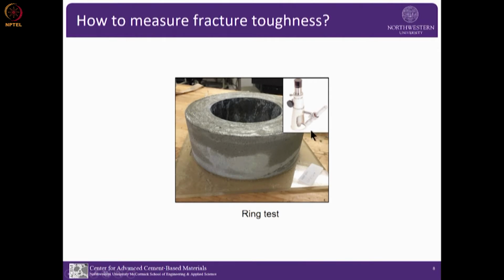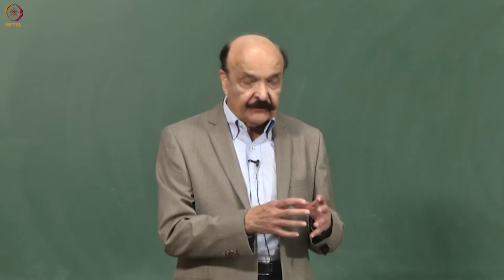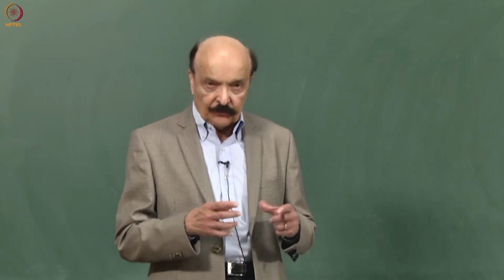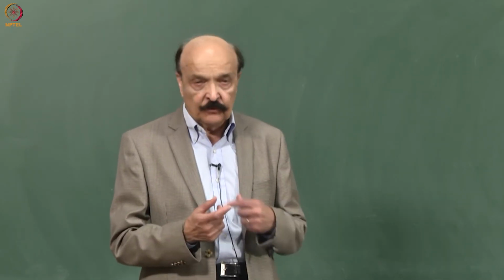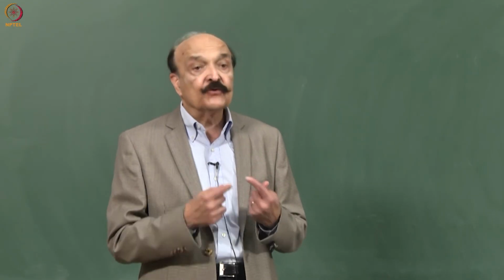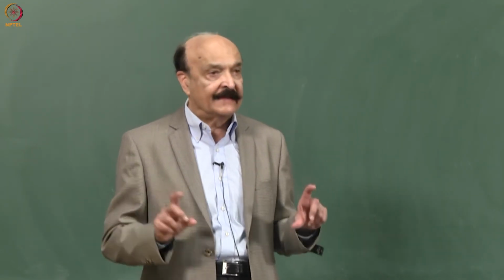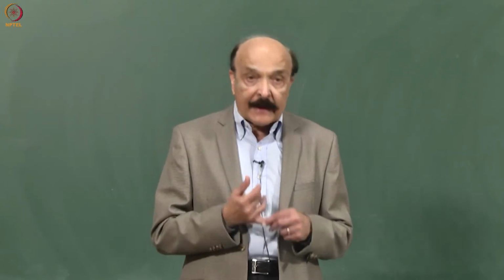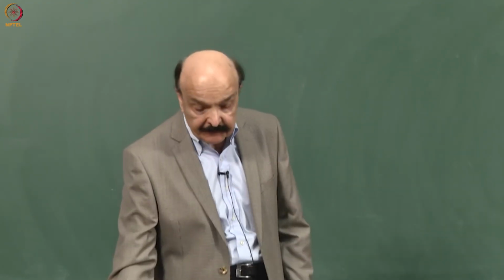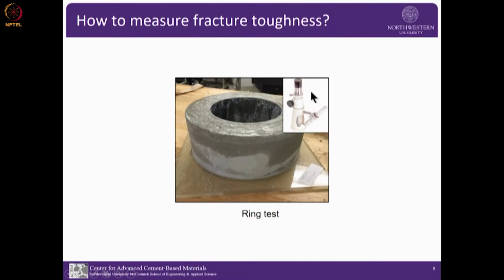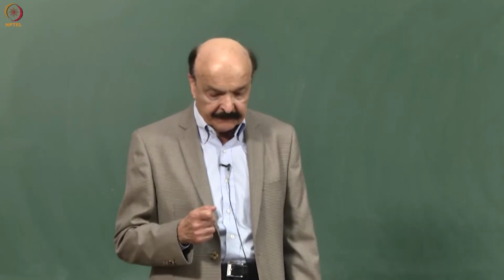In a ring test, you have a concrete here, and there is a steel ring which is relatively rigid. So after curing, you put concrete into drying. Concrete wants to shrink, steel says no, so you develop tensile stress. And because of axisymmetric, it's like infinitely long tensile specimen. So you find out when the crack starts, and then using microscope how wide the cracks are. This test now has been standardized by both ASTM as well as highway department in US.